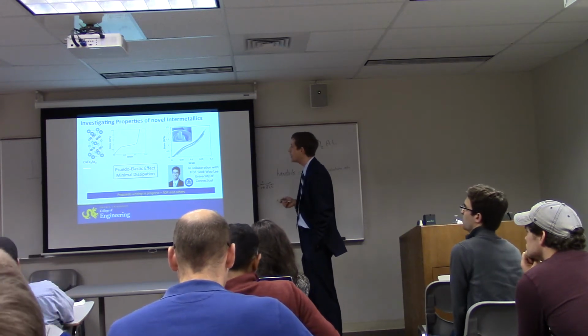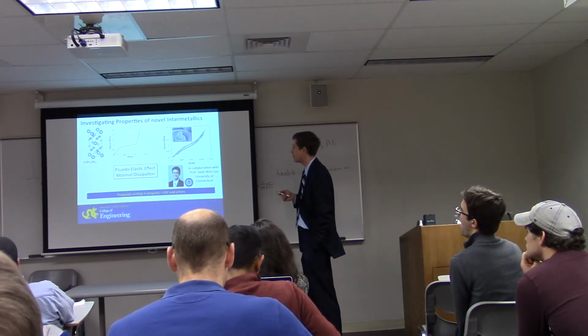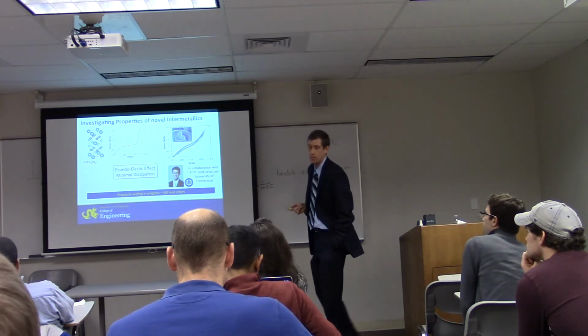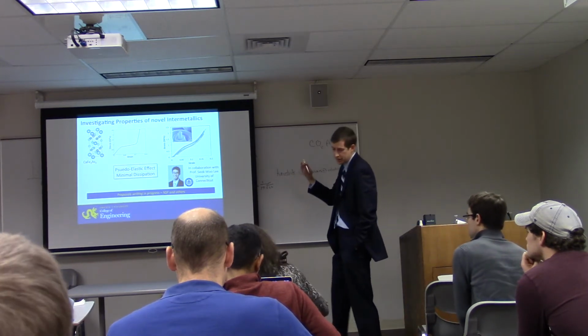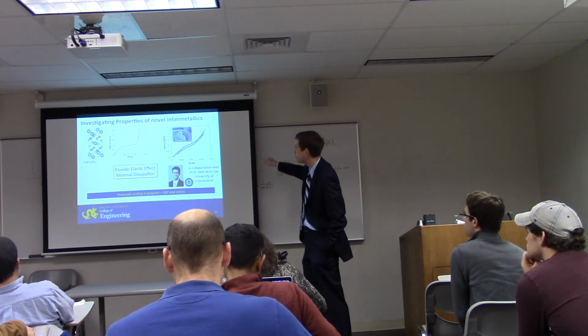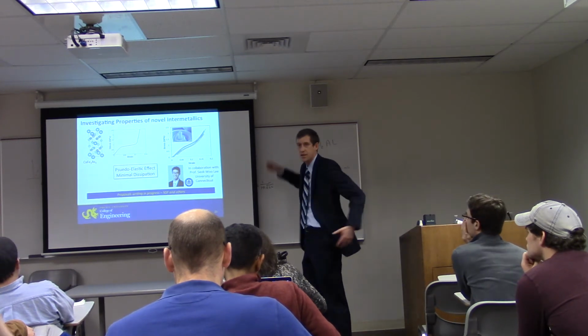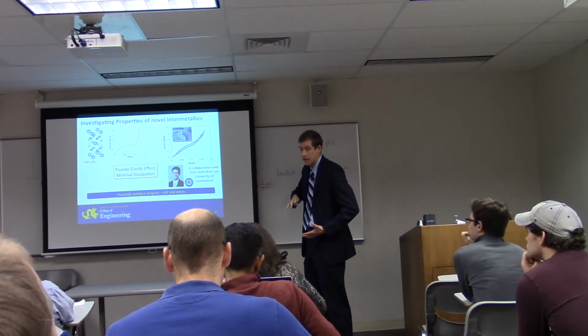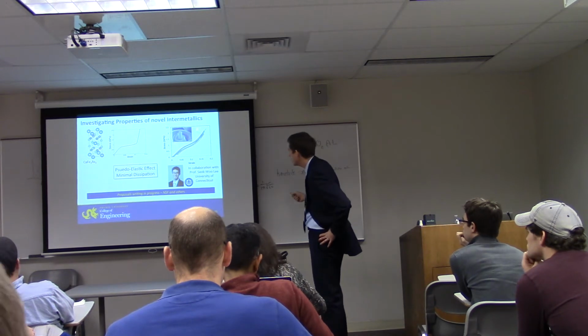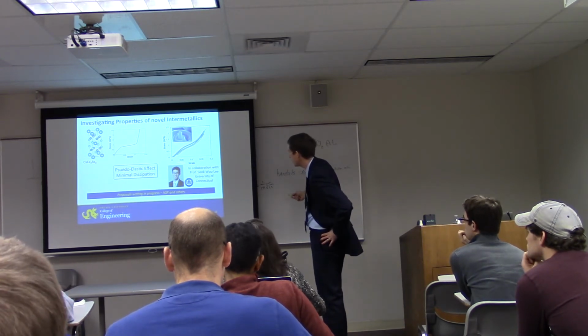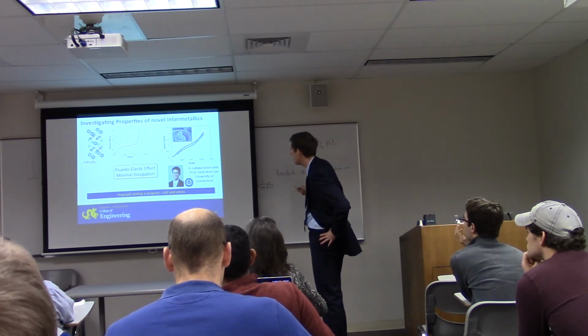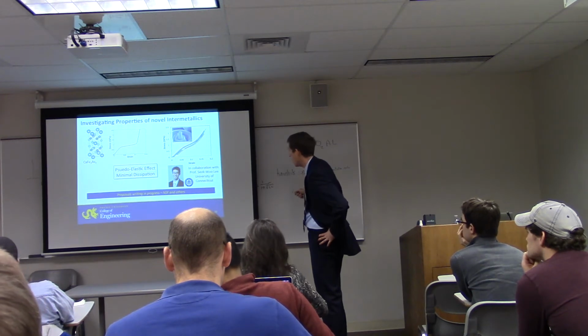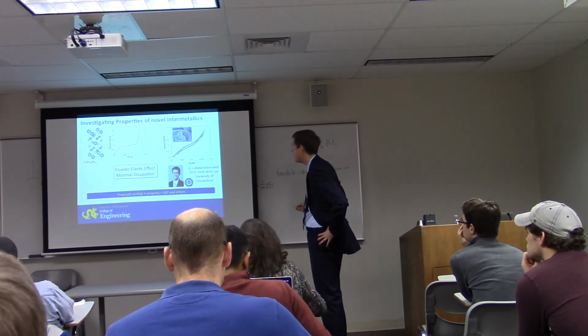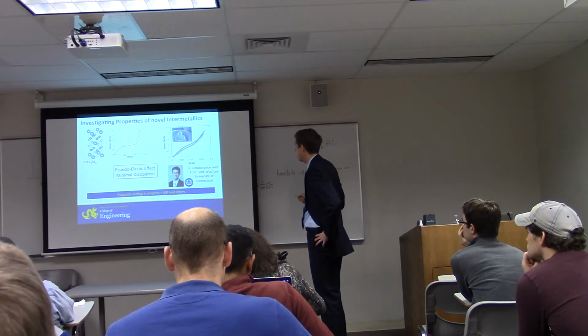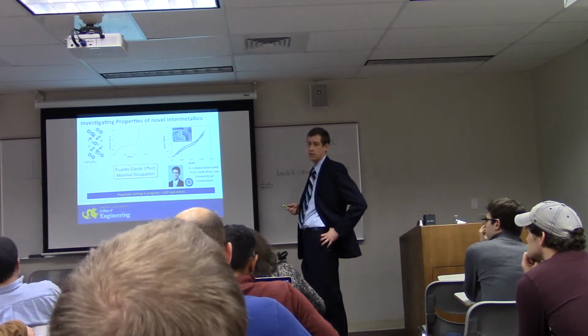The great thing about this material is that it goes through a number of phase transformations. At room temperature, it's antiferromagnetic, but if you compress it along the C-axis, it will transform to non-magnetic. As you can see in Suckwoo's experimentally determined stress strain curves, you get a reversible pseudoelastic effect with very little dissipation and probably 15% strain.